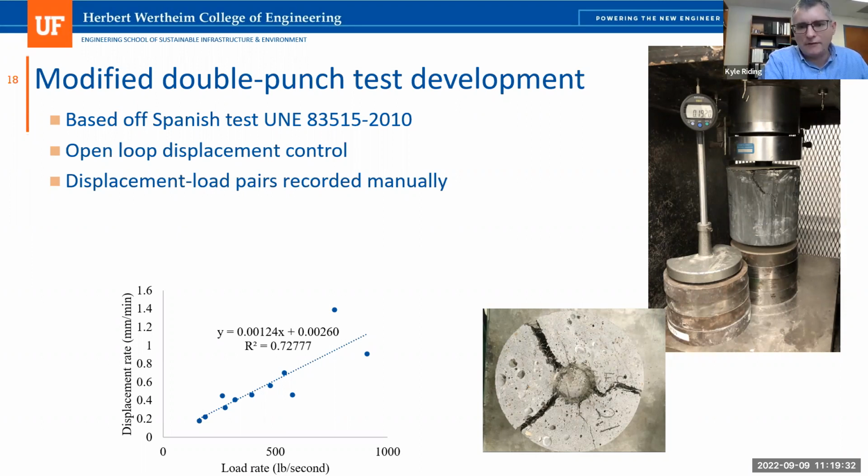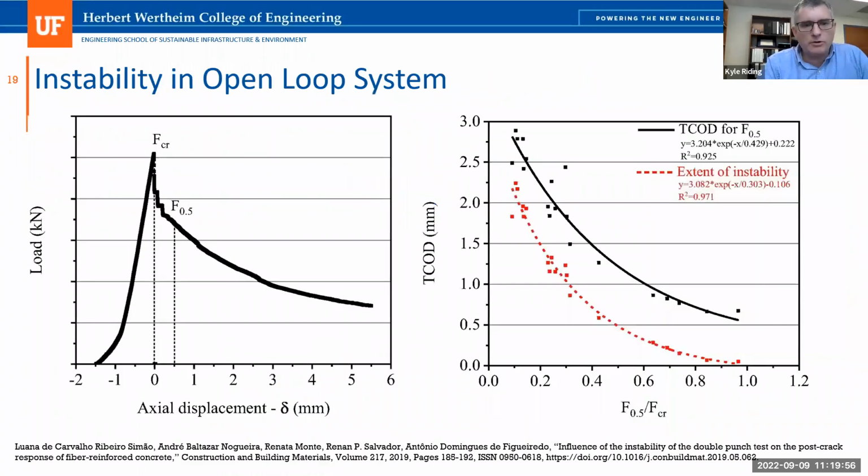Okay, so basically after your peak strength, after you start to get some failure of your sample, the question is then your sample can release some strain energy, and if you use plain concrete, you would get a sudden release of energy and a sudden change in strain very quickly. And so that would create an unstable system having that energy released. With ultra high performance concrete, however, you don't get that. You have a ductile behavior where you don't get that sudden elastic strain release of your material.